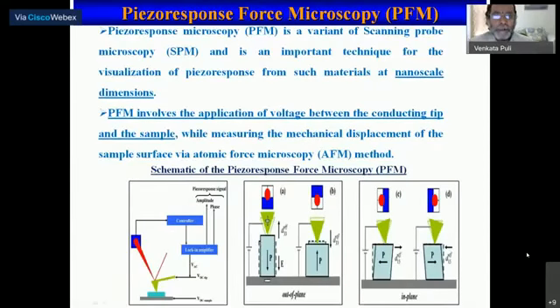Then we went to the nanoscale polarization. We used the PFM technique to measure the nanoscale ferroelectricity as well as the ferromagnetic properties of these multiferroic films. PFM is a variant of scanning probe microscopy, an important technique to visualize the piezo response of the films at nanoscale dimensions. It involves the application of voltage between the conducting tip and the sample. Here you can see the schematic diagram, and we can measure both out of plane and in plane for the films.